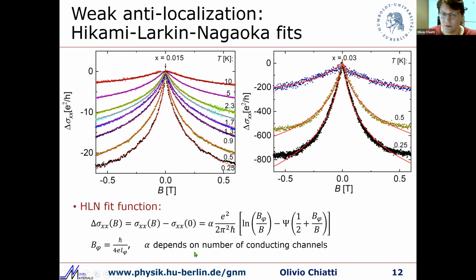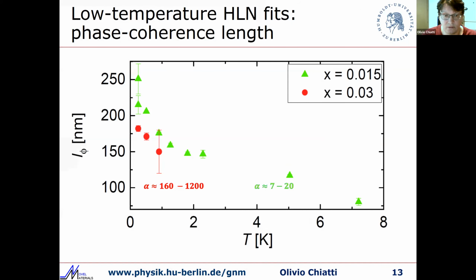Now, we have already seen in our work on bismuth selenide that alpha can be large if we have more than one conducting channel, which is a hint that the conduction in a system like this can be more complicated. On the other hand, the phase coherence length is more robust in the fits and doesn't depend on the number of conducting channels. So if we plot this as a function of temperature for the different curves, we see that the phase coherence length decreases with temperature as we expect. The values for the alpha parameters are still large, which is a hint that we don't have one single topological surface state conducting, but we have a bit more complicated system.